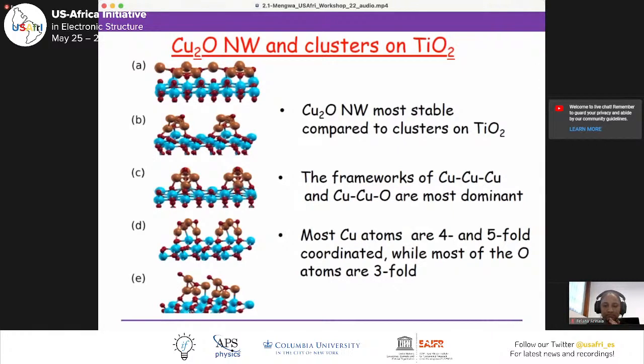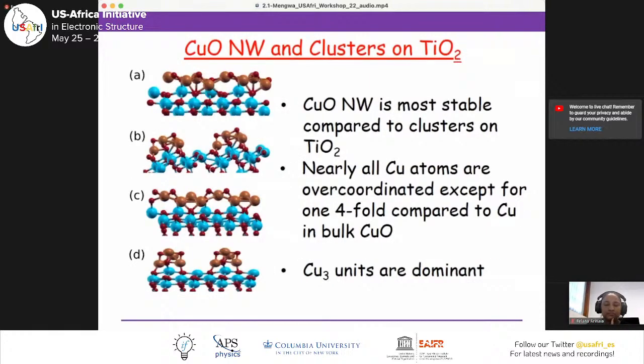The Cu-Cu-Cu and Cu-Cu-O frameworks are the most dominant, and most of the copper atoms are over-coordinated. Four are over-coordinated, actually 4 to 5-fold coordinated, while most of the oxygen atoms are 3-fold coordinated. The nanowire has a planar symmetry on TiO2. Similarly to CuO, the nanowire is the most stable on TiO2.